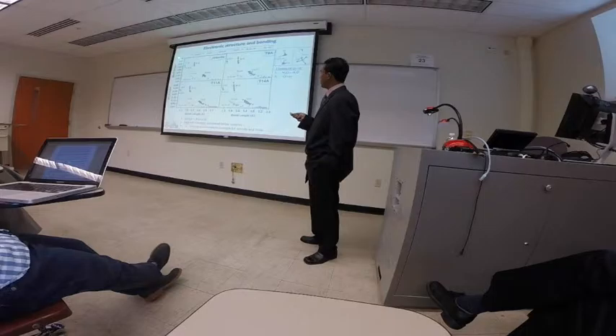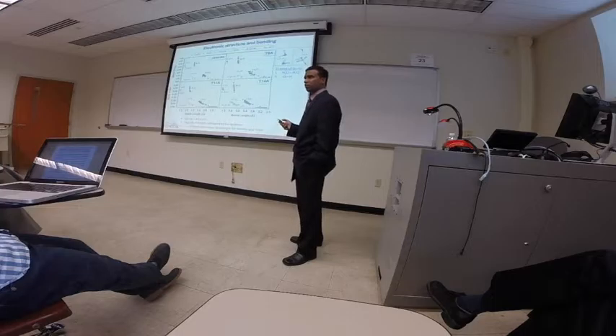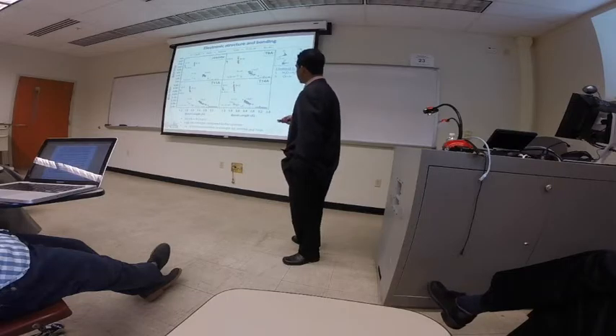Now let's focus on the electronic structure and bonding of these 4 crystals. So here you have a scatter plot of bond order versus bond length. This plot makes it easier to identify what types of bond you have and the strength and distribution of the bonds. As one may expect, you have 4 main types of bonds: the silicon-oxygen bond, calcium-oxygen, the covalent OH bond from water or hydroxyl, and also the hydrogen bond. And one can see the dispersion, or the broadness, of the hydrogen bond in both bond length and bond order.